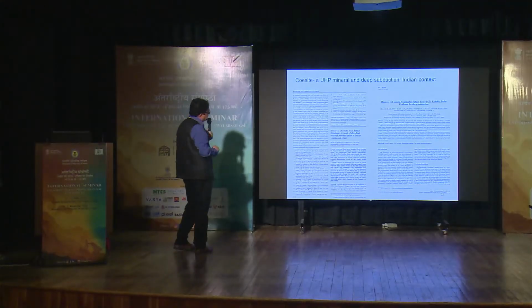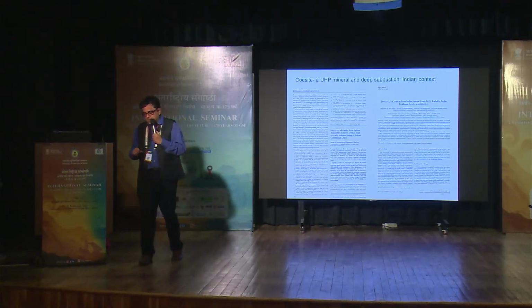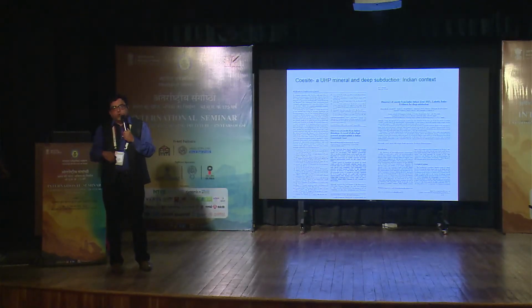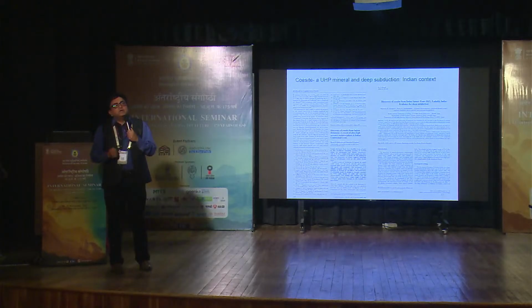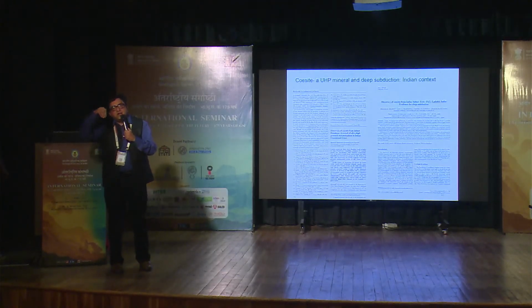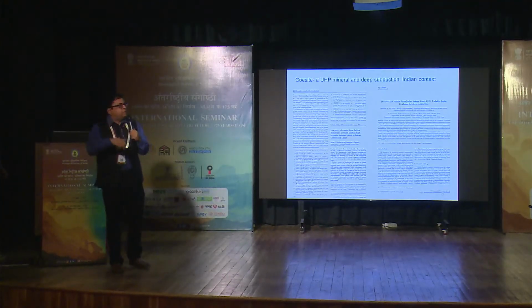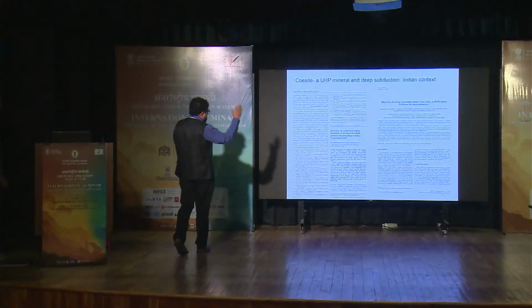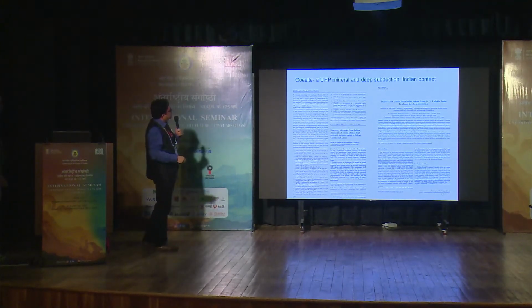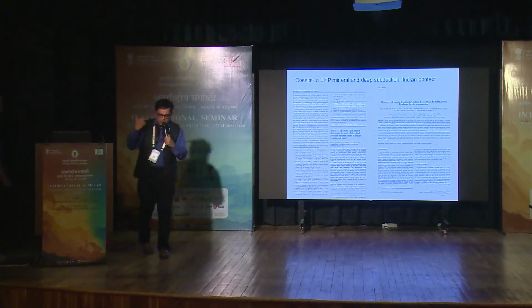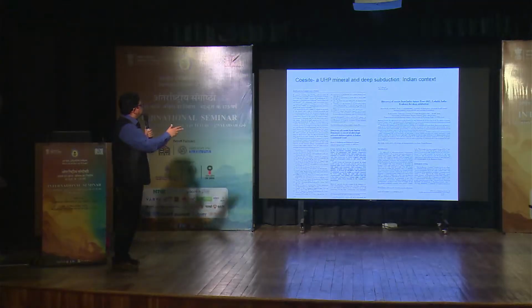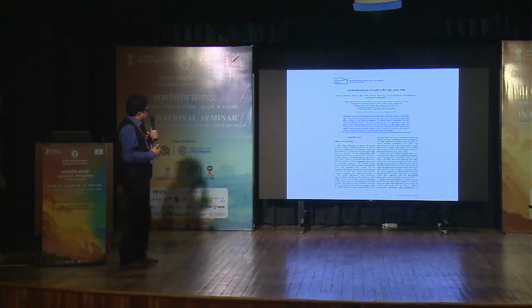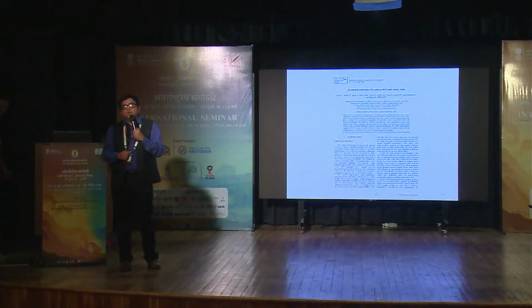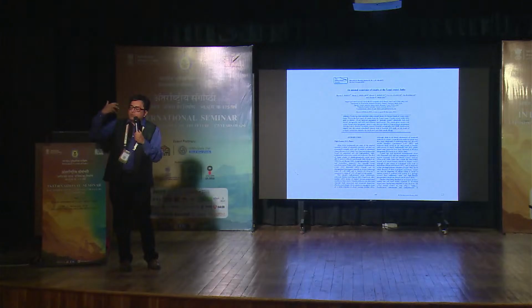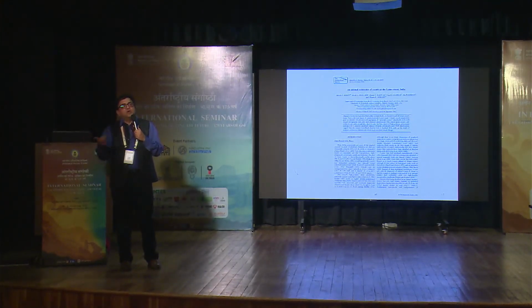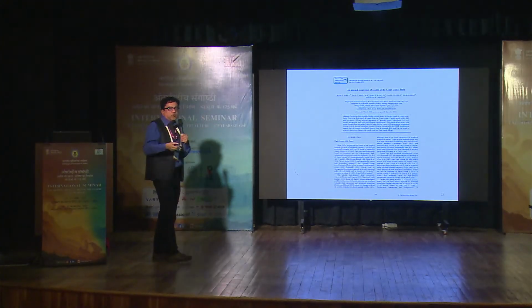So what this discovery tells us is, everyone knows that the Indian plate is subducting below the Eurasian plate, but how far is that plate going, what is the concrete proof? The discovery of eclogite tells that this plate has subducted at least up to 100 kilometers where coesite is stable, and it was brought up. So these two papers, the discovery of coesite from the Indus suture zone, made people look more seriously at ultra high pressure mineral assemblages. Next one. Of course, coesite can also be formed by shock metamorphism. If a meteorite hits the surface and there is a sufficient amount of silica, then it can generate coesite, as was recorded in Lonar Lake. That is the other way you can generate coesite.